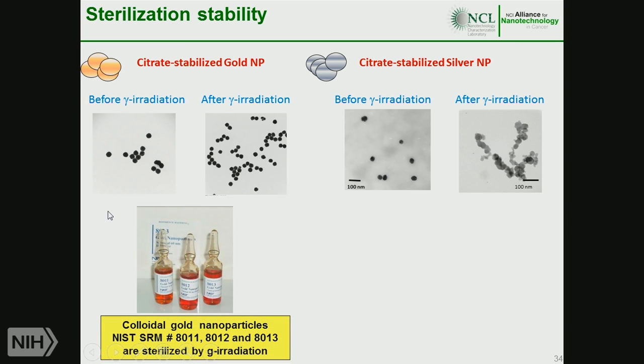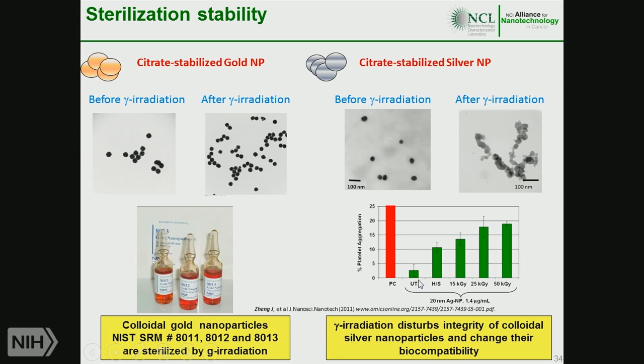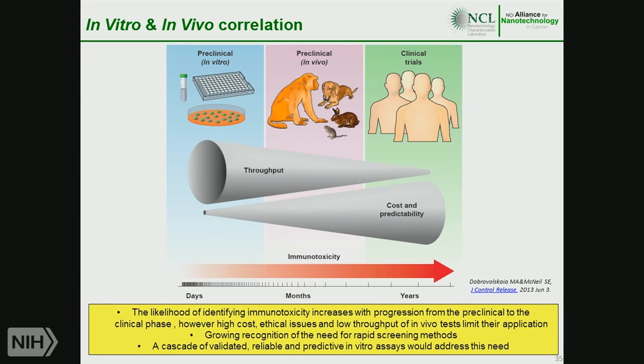Gold colloids are sterilized by gamma radiation. In fact, the National Institute of Standards and Technology produces standard reference materials that are sterilized by gamma radiation. In the case of the silver colloids, not only does the shape of the particle change and its integrity is affected, but their biocompatibility is also affected. You see, the particles before sterilization do not react with platelets and do not cause platelet aggregation, but after sterilization, and as we increase the dose of gamma radiation, these materials change and then they become reactive with platelets. So we have to be very careful in selecting a sterilization method which would not affect the integrity of the particles, which would not harm drugs that the particles carry, and also which would not change biological properties of these materials.